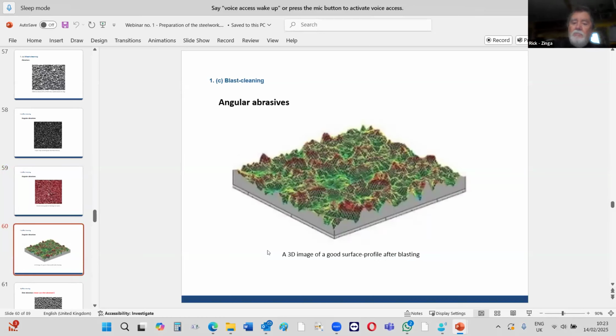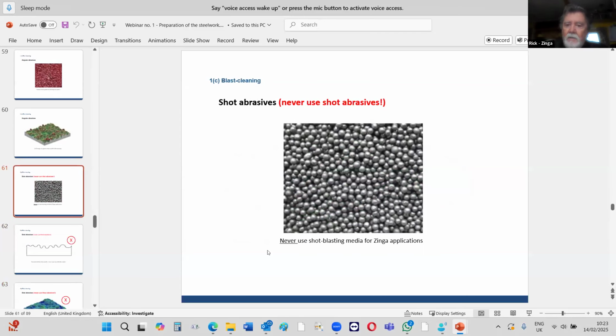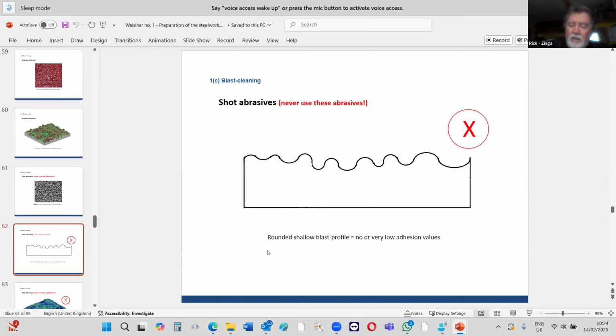So this is to give you an idea. This is a 3D image from a computer. It had a machine with a little stylus, and that needle traced all the peaks and valleys in the blast. And if you look along the outside edges, you can see how deep it goes. The nice sharp edges right deep inside. This is a big no-no, as Abe was showing you on his quiz. This is why you never ever use shot blasting, okay? Because that's what happens. It's rounded off.